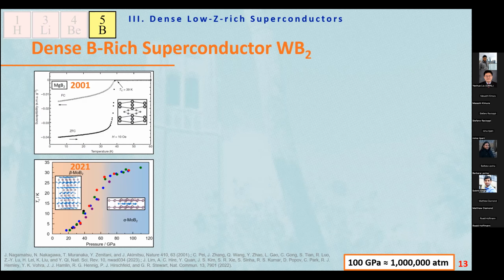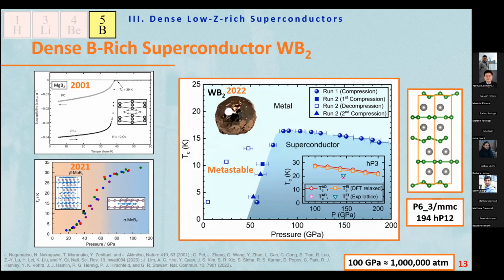We work with a theory team, a synthesis team and a high pressure team. Our theory team quickly calculated after seeing this result from the Chinese group on arXiv. We searched for other diboride superconductors, and then we found tungsten diboride. The theory team first suggested that tungsten diboride in the MgB2 structure is a good candidate to have a relatively high TC. And we quickly made this sample in the synthesis team, and here is a beautiful picture of the sample.